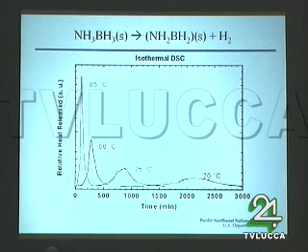And so you go back to the isothermal DSC experiments or with the mass spec, and what you see is you can take this solid and heat it up to various temperatures: 65 degrees, 70, 75, 80. It's an activated process. At higher temperature, the stuff comes off faster. So can we do some sort of simple treatment on this to get an activation barrier for this material?